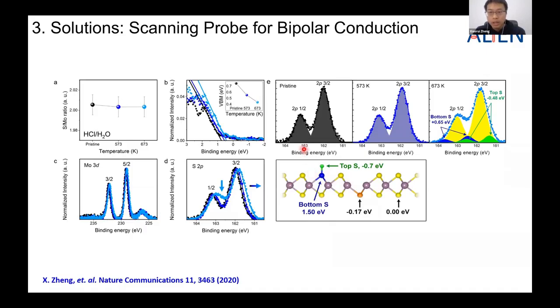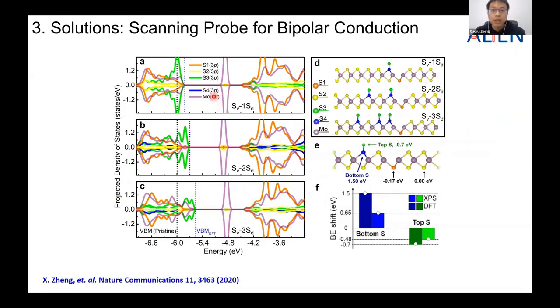This is our proposal. And after the XPS measurement, we did DFT calculations by introducing different numbers of this sulfur-sulfur bond, like 1 sulfur bond, 2 sulfur bonds, and 3 sulfur bonds. We calculated the DFT results and kept tracking the evolution of the valence band maximum. And you can see, as we increase the number of sulfur-sulfur bonds, the valence band maximum shifts towards the right, and this corresponds to the Fermi level shifting downwards, corresponding to p-type doping.